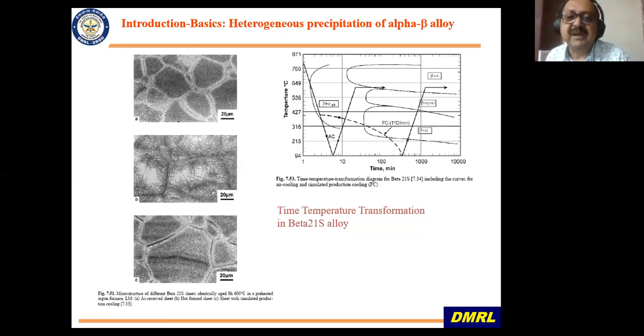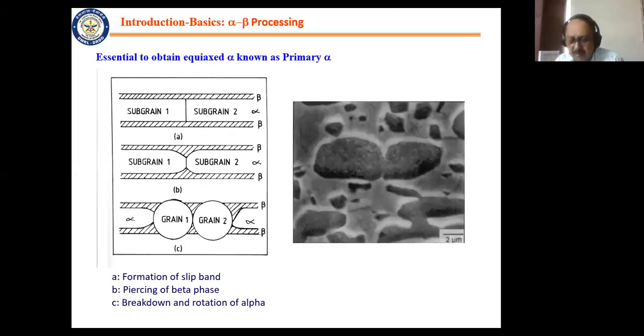The other very important aspect where titanium alloy differs from steel is, if you want to globularize, most of the time you will see that alpha and beta precipitate as lamellar structures. Now, if you want to make it globular, it is not possible just by heat treatment as in steel. What you have to do is deform. Once you deform, this is the alpha layer, this is the beta layer. Dislocations are introduced and subgrains form, and when you annihilate these subgrains, they recrystallize, and you get what is known as globular alpha.